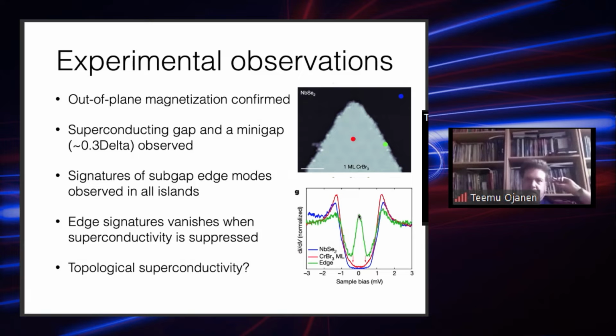So this tentatively would be a signature of the topological edge mode, which would somehow be traveling around the edges of the sample. Right. And this type of signature, this enhancement in the edge local density of states, or edge dI/dV, is systematically observed on all magnetic islands.